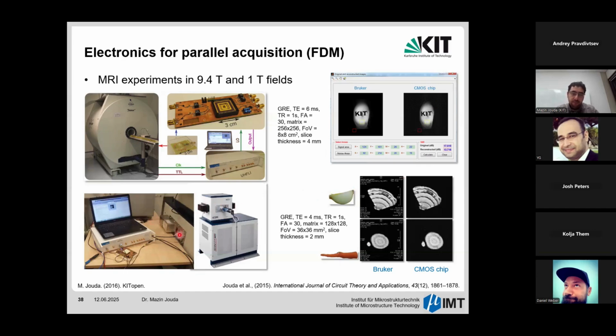In a low field system, we use the chip, but we also use external preamplifiers with the chip, and we could see that with external preamplification, we could enhance the noise performance, and we could get more or less similar quality as commercial spectrometers. And both experiments show that the chip can work over a broad range of frequencies from a few megahertz to around 700 megahertz. And then we can effectively combine 8 channels together and acquire them using one single channel of the local amplifier. So that shows the potential of CMOS electronics in tremendously reducing the complexity of the NMR and MRI hardware.